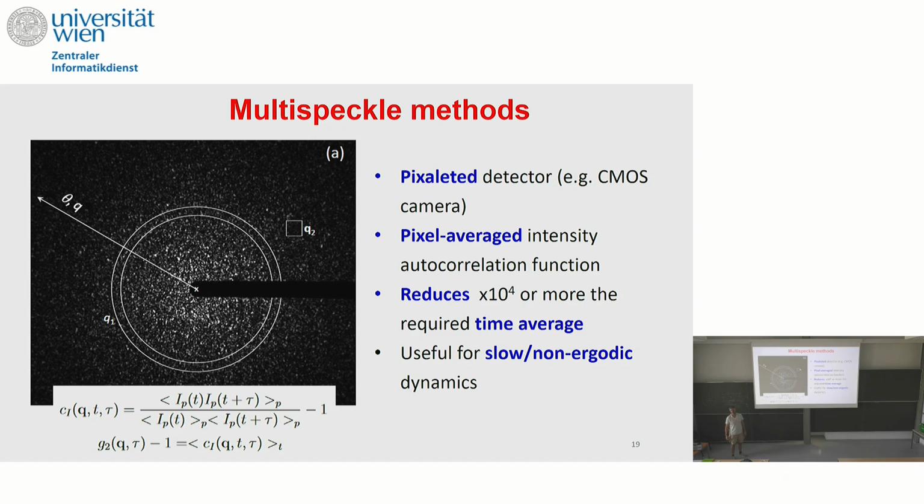I mean, you do an average over angle, but again, it depends. If the sample is isotropic, the orientation of Q doesn't matter, so I can take the ring. If I'm doing shearing in this direction, for example, then no, I cannot do this ring average. I have to pay attention to the orientation of Q. How can you combine the data from different Q vectors?